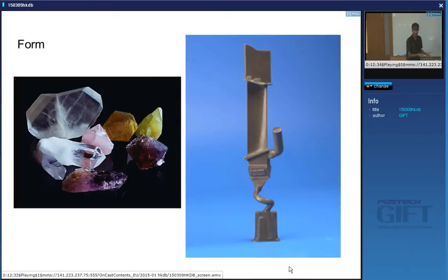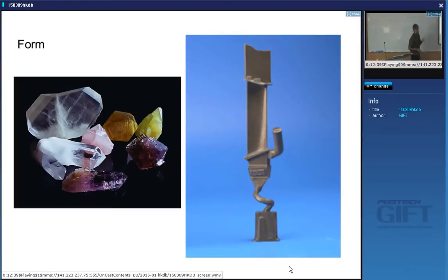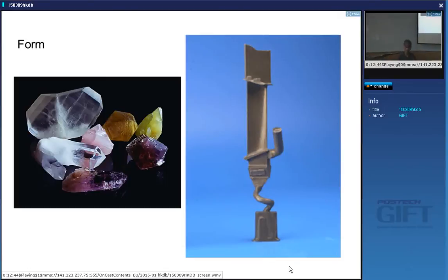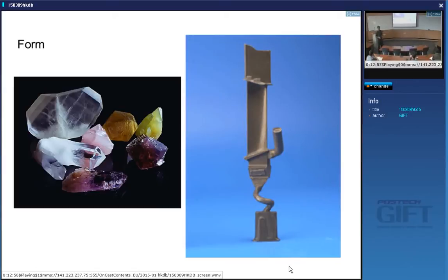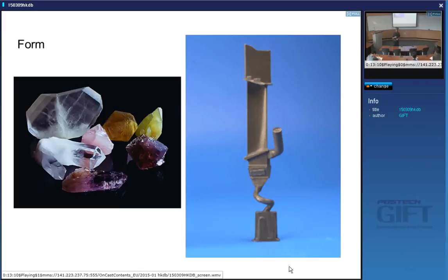In the turbine blade, you grow it along a specific direction so that the elastic modulus minimizes vibrations. You want as few vibrations inside an aircraft engine as possible. You can exploit both the absence of grain boundaries and the ability to grow along directions that minimize vibrations — the blade may rotate at 25,000 RPM.